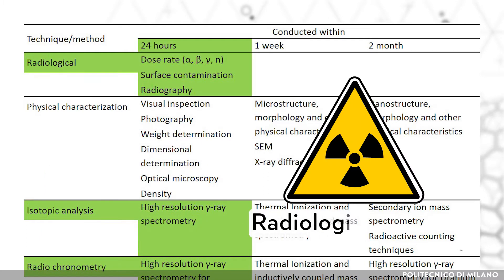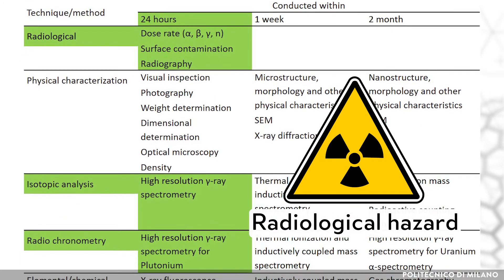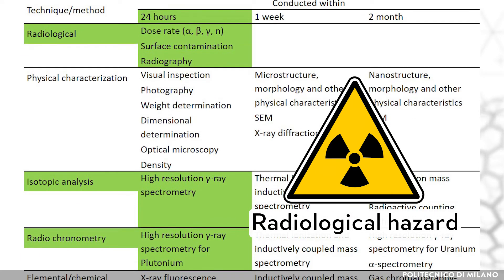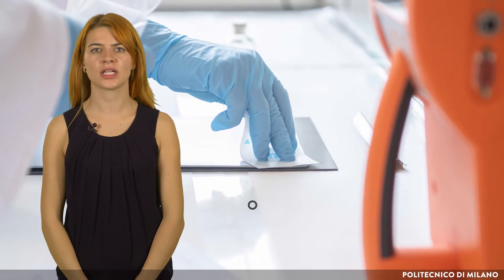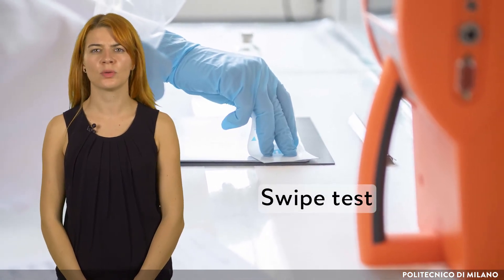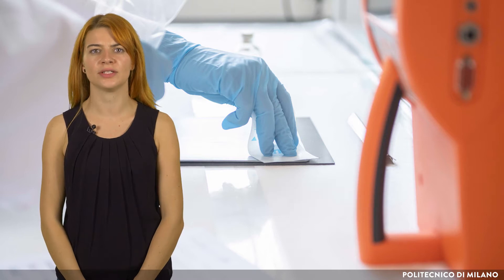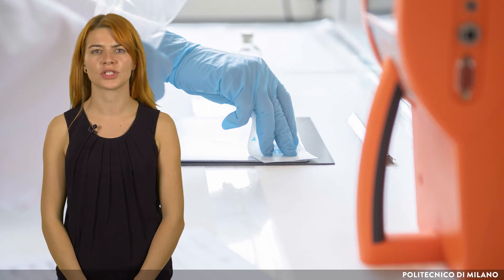The radiological hazard of the sample has to be assessed during the first 24 hours, for an estimation of the total activity and a test for surface contamination for safety reasons. For this, high-resolution gamma-ray spectrometry and swipe tests are used. Although most heavy nuclides like uranium or plutonium are alpha emitters, this decay is often followed by a gamma emission for de-excitation of daughter nuclides.